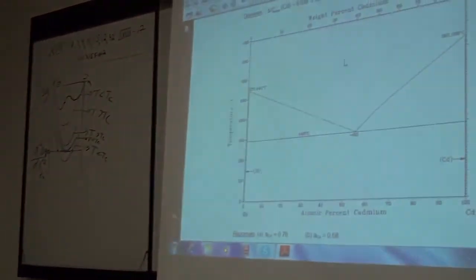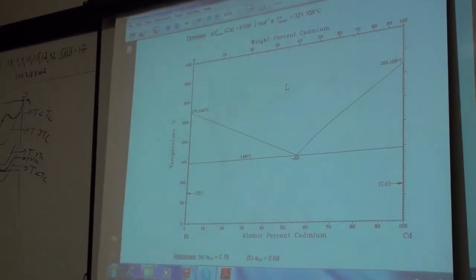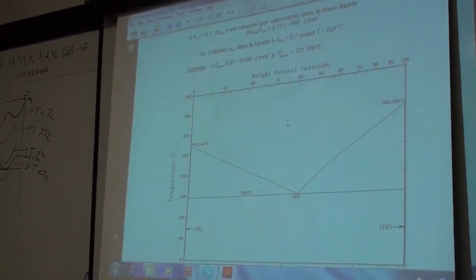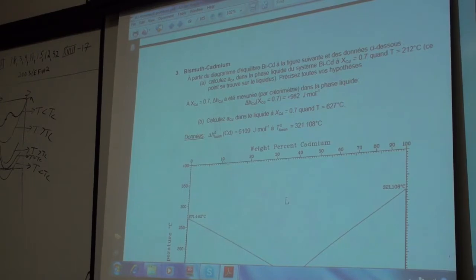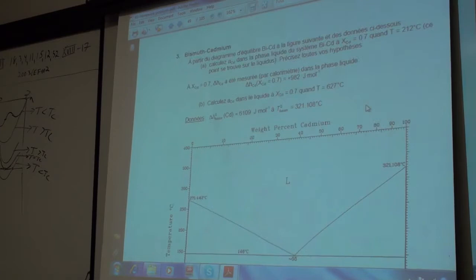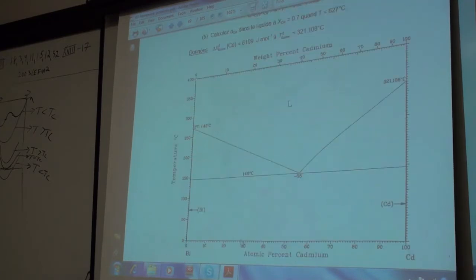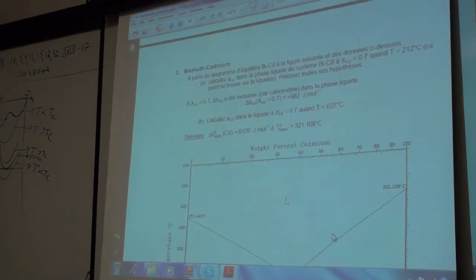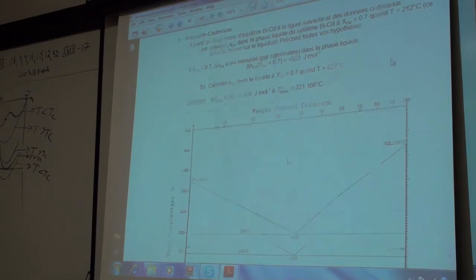Okay, here's your bismuth-cadmium phase diagram, which we're taking to be a simple eutectic diagram. I have simplified this a little bit. There's actually a little bit of solid solubility, but let's say there isn't. From the bismuth-cadmium diagram, slightly simplified, calculate the activity of cadmium in the liquid phase at X cadmium is 0.7 at 212 degrees. Okay, so X cadmium is 0.7 would be over here.